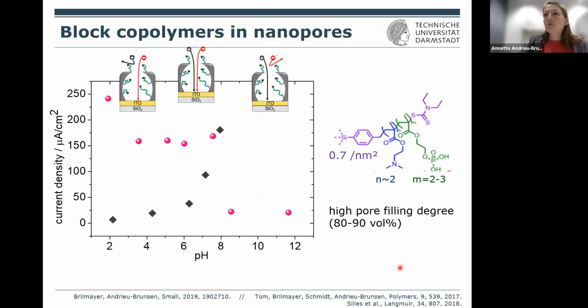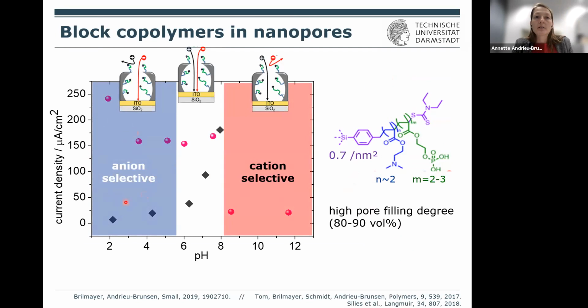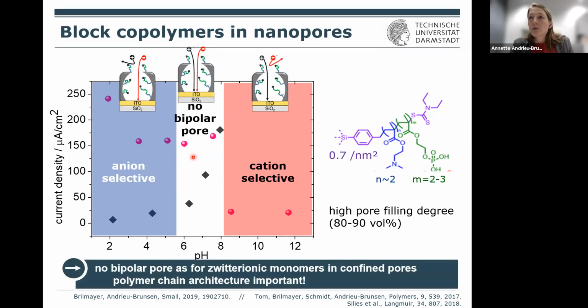The next question then, of course, comes up: does this have to be a zwitterionic polymer? Or what actually happens if I now have a controlled polymerization in hand and I'm reinitiating the polymerization? So I polymerize 2-3 monomers of this positively charged polymer, and then another one that can be negatively charged or neutral. And we did this with the question of how the chain architecture actually influences the transport. And what we see is that you go from an anion selective region to a cation selective region. And the interesting part here in between, in the middle, we do not see a bipolar pore. So at least for this system, we would conclude that the chain architecture has an influence and that it's not sufficient to just combine the two countercharged parts to get a bipolar pore. There has to be more, and it has to be combined maybe closer in one monomer.